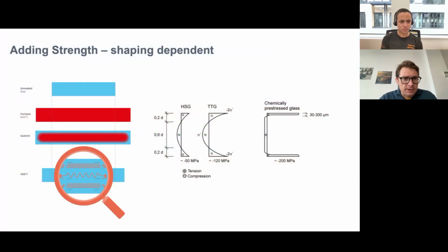Well, if we take this small diagram on the left, the dotted lines running down really relate to the length of the glass. As we heat it up, like most materials, it will, at 650 degrees, soften slightly. It will also expand. When it comes out of that furnace and goes into the air quench, the outer surface of the glass is cooled back down below that glass transition temperature. And while the inner core cools at a slower rate, that then pulls in the outer glass, creating tension on the inside of the glass and a compressive crust around the outside of the glass.